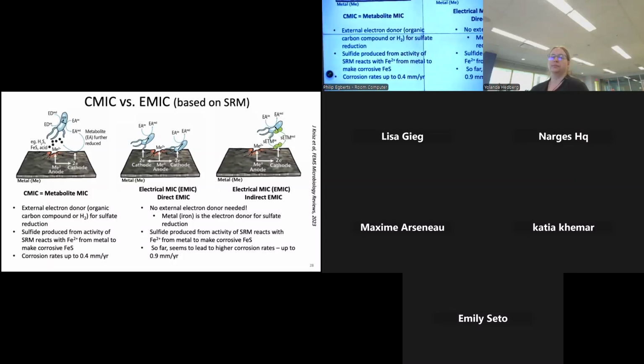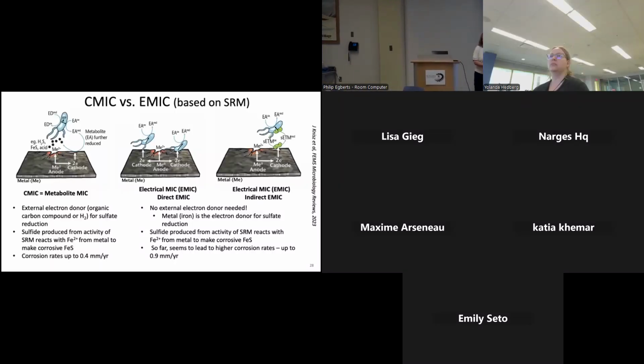These are some figures from that paper I suggested you take a look at, if you're interested in microbial corrosion, just to summarize CMIC versus EMIC. In CMIC, or chemical microbially influenced corrosion, we have that external electron donor. Sulfide produced from the activity of those sulfate reducers reacts with iron 2 to make that corrosive FeS. The rates typically have been reported to be about 0.4 millimeters per year on metal pipelines.